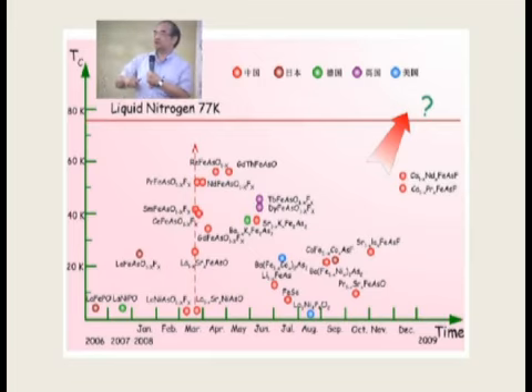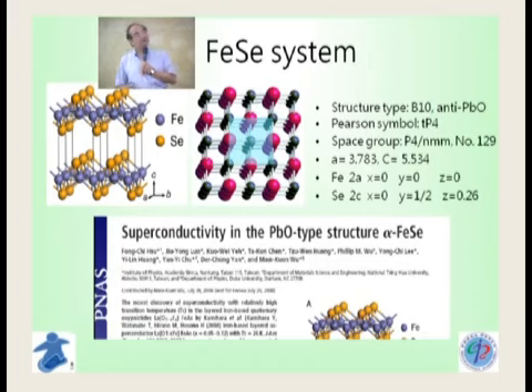However, this discovery does bring up something really important fundamentally. So in the next 10 minutes or so, I'll tell you what we think is important for a better understanding of superconductivity, from the fundamental point of view. I'm going to use a system we discovered in 2008, the so-called 1-1 system. Look at that structure, it's so simple. It's basically a so-called infinite layer. You have iron as a point, then the selenium up and down forms a perfect